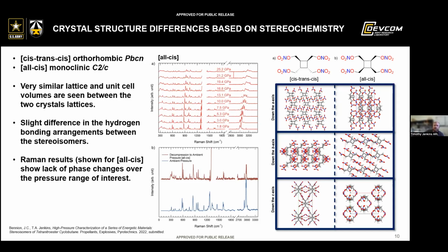And in fact, if you look at the change in pressure with Raman, you can see pretty much that we don't have any new features that show up. We don't have any large phase changes or even very small phase changes. We do see a lot of peak broadening under pressure, as you would expect from going up to relatively high pressures. These materials are not very hard materials, so they have an elastic response, but they do show a lot of peak broadening over the course of the pressure range.